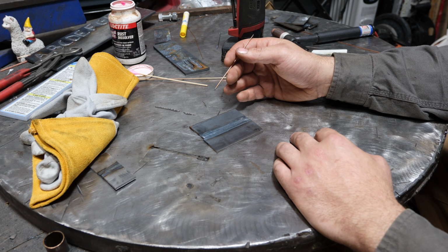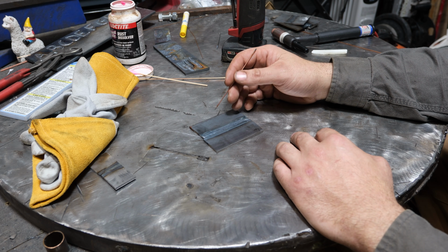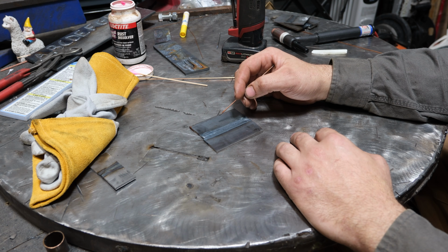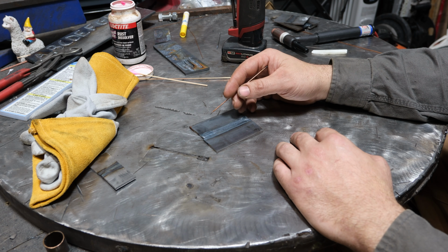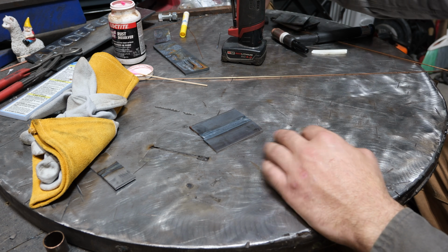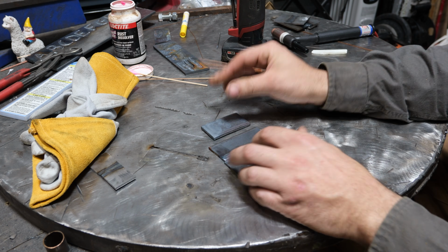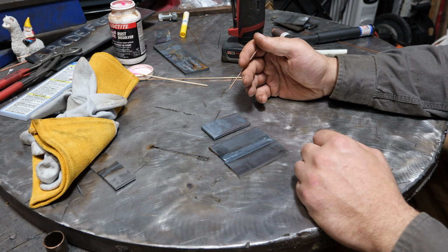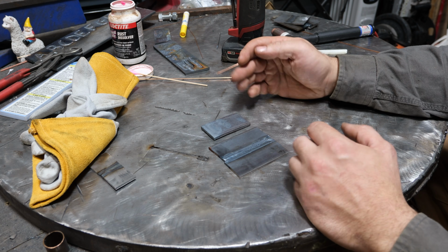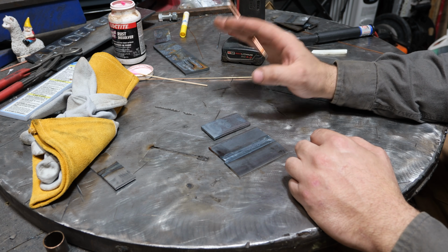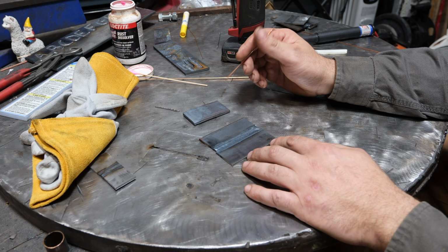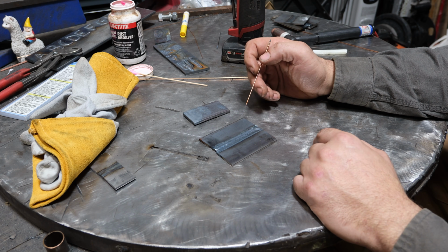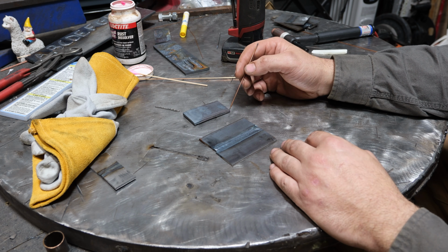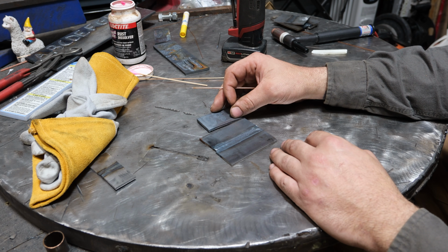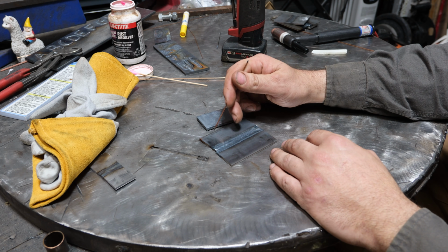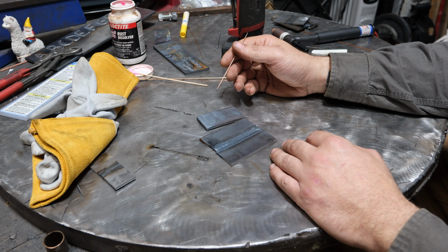And speaking of joining two pieces, I cannot stress the importance of having a proper fit up. TIG is one of those things that, yeah, sure, you can bridge a 1/2 inch gap with it and make it work. I mean, your weld is going to be trash, but yeah, you can, because you have that foot pedal to control heat input. So you can bridge gaps that no other process could even dream about. But the problem is that when you get to having poor fit ups like something like this, and you're trying to weld all of that straight through, guess what?